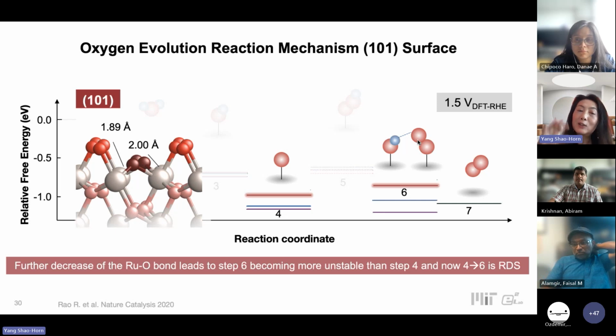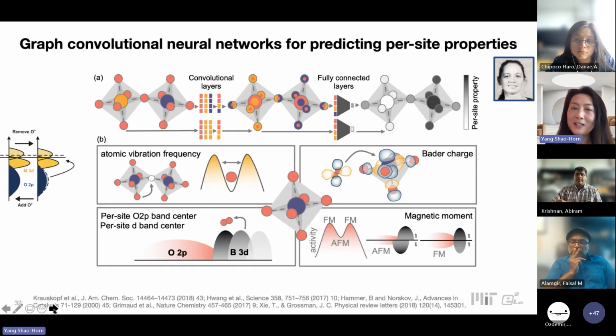And our surface is no longer covered by the superoxide species, but is passivated by O-terminated surfaces. So this essentially provides insights that not only tuning the chemistry, but tuning the specific moiety or surface electronic structure is very important. So essentially through chemistry, you can tune the electronic structure of individual oxygen and tune the surface atomic structure.